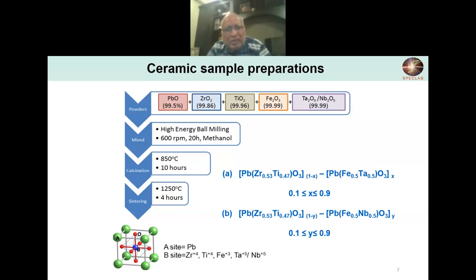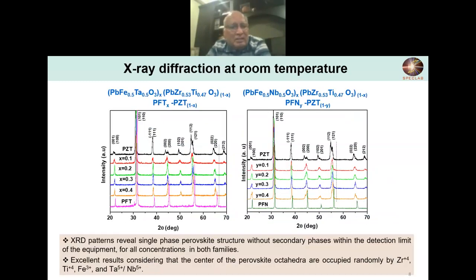And in the next one, you'll see the X-ray data. In the XRD data, you will see that all these materials only show peaks of perovskite structure, and no phase mixing of any kind was observed. It became really a single phase material, even though it is a complicated material, considering that the B site is occupied by several ions, like titanium, iron, zirconium, and tantalum or niobium. This XRD spectra shows that it is indeed a very good material that was obtained. So we did both for the PFT as well as PFN. You can see them all here, PFN and PFT.